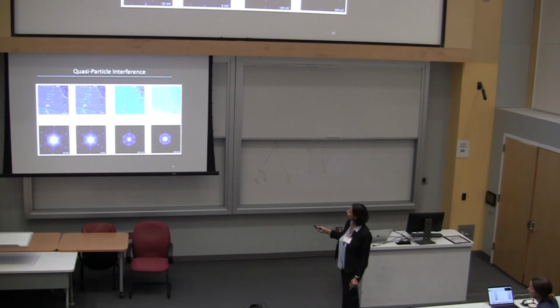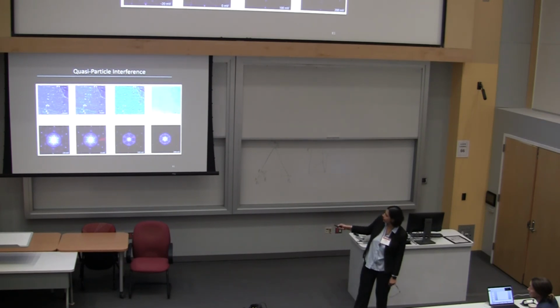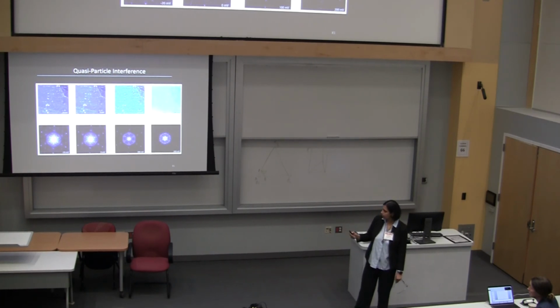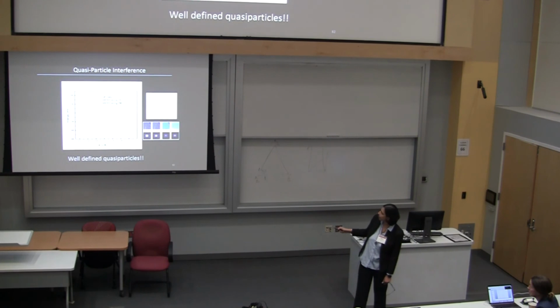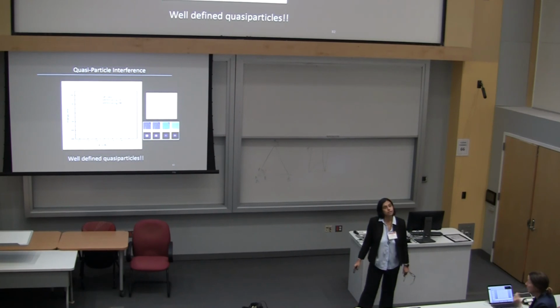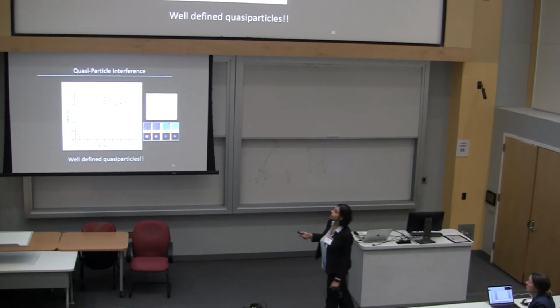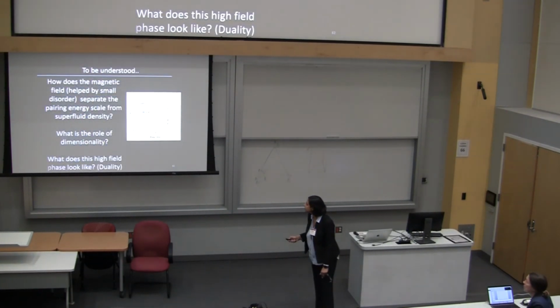In the case of niobium diselenide, we see clear quasi-particle interference. These rings, right? You can see the dispersion. The size of the ring gets bigger. And you can actually compare our dispersion in red with green, which is the data taken from ARPES. So in any case, we have good quasi-particles.